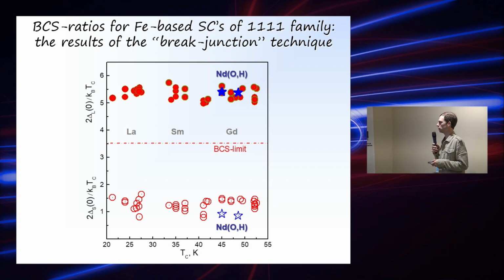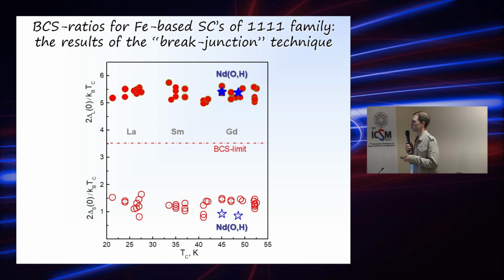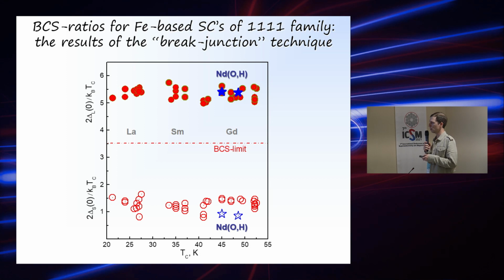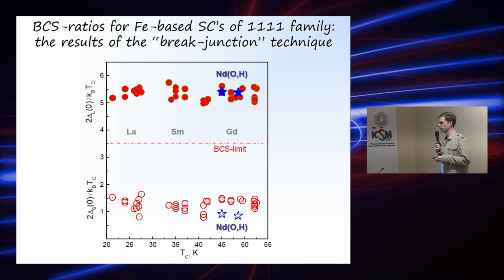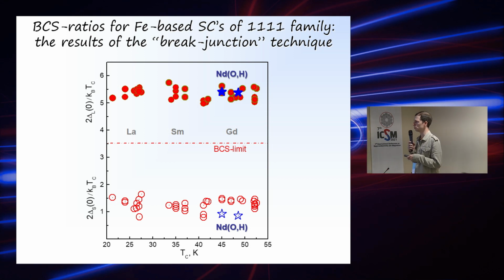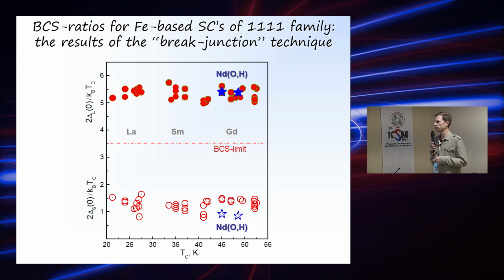But one could say that probably it means that we have found nothing new. But from the other side, the main result of this work is that due to this substitution, which introduced not only the electronic input but also the influence of the hydrogen atoms, we found that the influence of the effective bands with a small gap strongly decreased, up to the total impossibility to detect it experimentally.